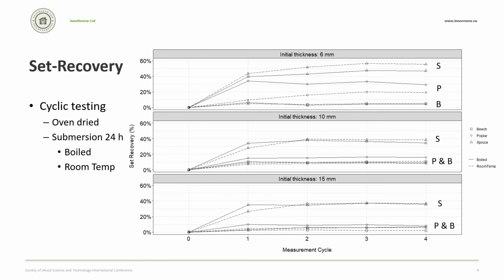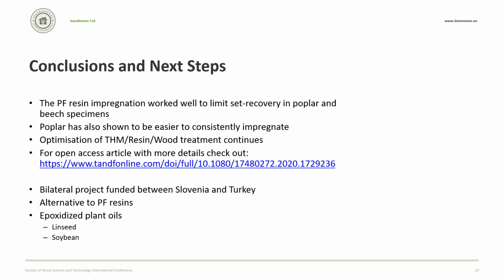For the other 2 groups, poplar and beech performed well, with values below 20% for samples compressed from 10 millimeters to 5 millimeters, and values below 10% for samples compressed from 15 millimeters to 7 millimeters. We have found that PF resin impregnation and curing during densification successfully limited set recovery in our poplar and beech samples. For more information on this study, you can visit the open access article through the link provided.